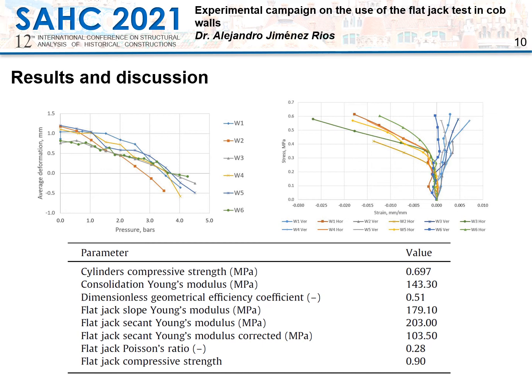On the other hand, the secant Young's modulus value, obtained with equation 26 in accordance with RILEM MDT.D5 and corrected by using a value of k_A of 0.51, resulted to be roughly 50% less than the value obtained from the slopes of the stress-strain curves. Therefore, it is advised not to correct the values obtained from the stress-strain ratio as specified in ASTM C1197. The uncorrected values give a more accurate estimation of cob's Young's modulus.